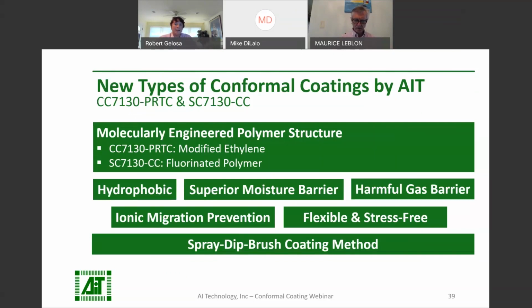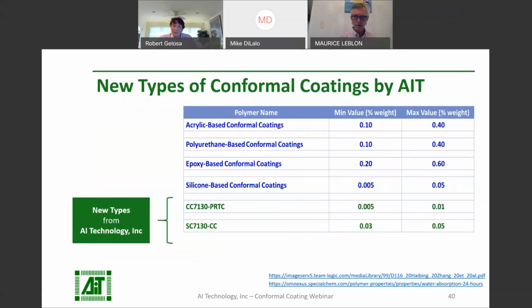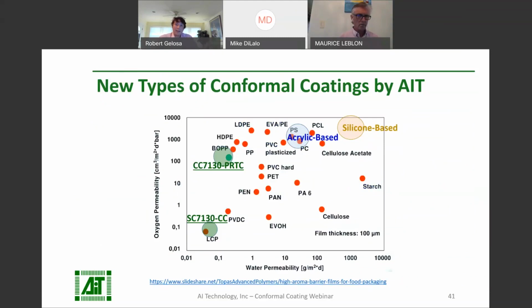CC7130 PRTC is a modified ethylene type, and SC7130CC is a fluorinated polymer type. They were carefully designed to balance all of the attributes needed in today's conformal coatings. They're hydrophobic with low water absorption. These coatings were molecularly engineered to meet the challenge of combining two important and sometimes seemingly contradictory properties. They have high flexibility and can stretch, but with small pore size. This way, the coating has a superior gas and moisture barrier, but won't crack or delaminate during difficult temperature cycling.